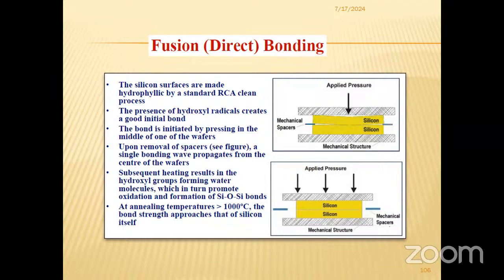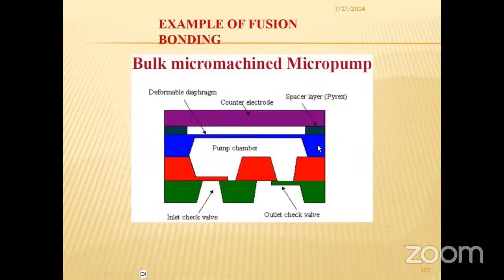It is made hydrophilic, and then pressure is applied, and huge pressure is required, and then annealing at greater than 1000 degrees centigrade, and now the silicon will bond together. This bond is called the SiO-Si bond, because first the silicon wafer has been made hydrophilic and some water molecules are present in between them. So the SiO-Si bond is a strong bond. It will not break further. This is an example of bulk micromachining, a micromachined micro pump. Here we can see 4 structures have been bonded through fusion bonding.